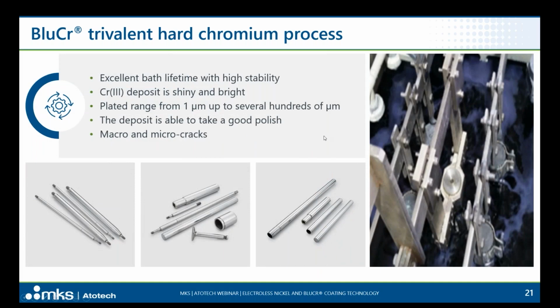On the right-hand side, you see the picture. So basically, this is just a picture from the top of our plating tank. You see in the middle the cylindrical part, which is the cathode, and on both sides you see anode bars with, in this case, graphite anodes. For the BluCr process, we use non-soluble anodes. This can be either graphite, or it can be MMO, metal mixed oxide coated titanium mesh, or it can be platinized titanium mesh. But important is that we do not need and we do not use anymore any lead substances as in case of hexavalent chrome.